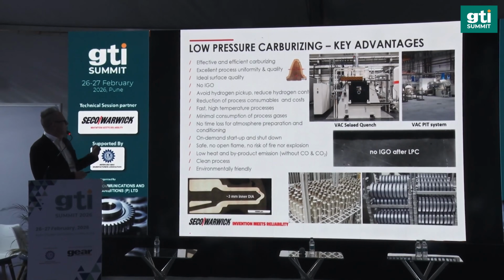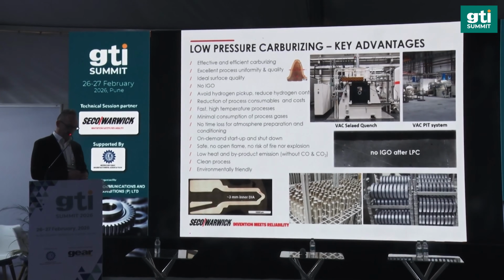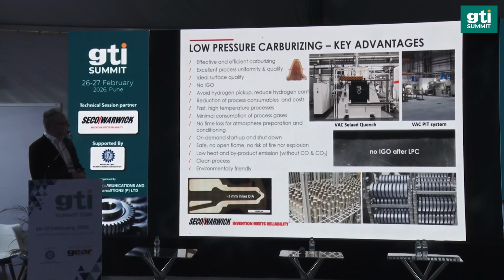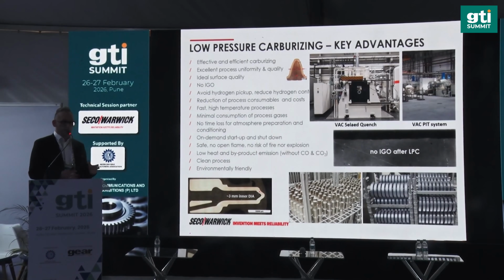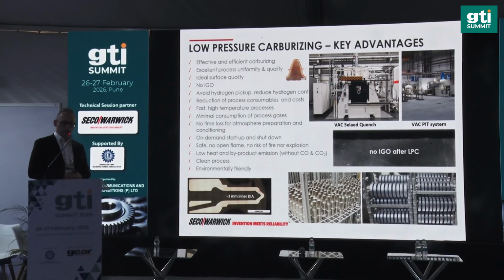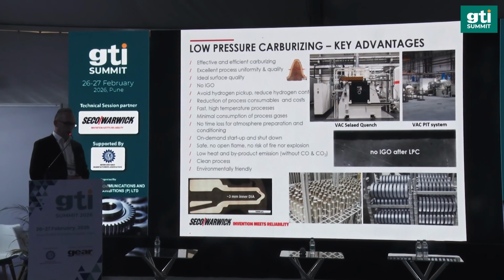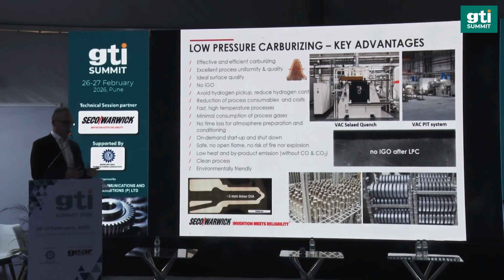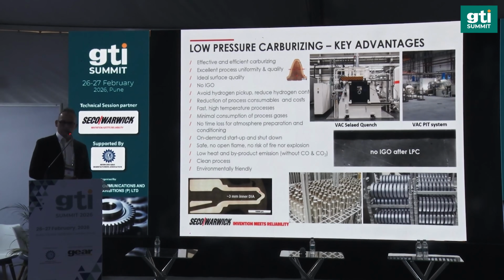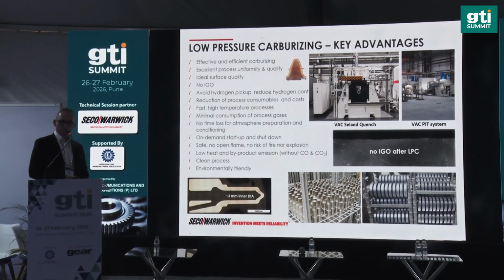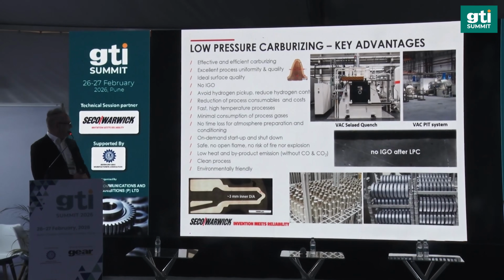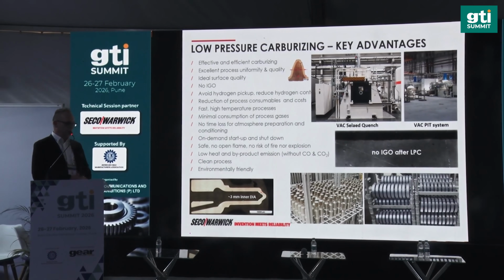One of the most beneficial elements of low pressure carburizing is no presence of oxygen, which means there is no intergranular oxidation during the whole process, which means that post-machining might at some point be excluded, as we don't have this element that tends to cause problems. We have ideal surface quality. I mean, the parts after processing are silver and shiny, so additional post-machining is not required. We can develop the process at higher temperatures, which means that we can shorten the process.